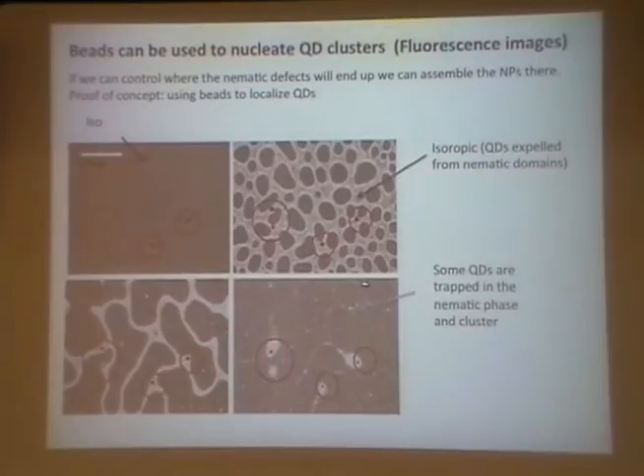Another interesting point here is, okay, this is remaining nematic phase now. Although these images only show quantum dots, the nematic phase would be here. Some quantum dots got left behind. You can see the paths they tried to take to get out of the nematic phase. And where they got left behind, they're in clusters. So we can see this thermodynamic effect, and then if they didn't make it, they cluster, they use the elasticity effect to also minimize the interaction with the liquid crystal.